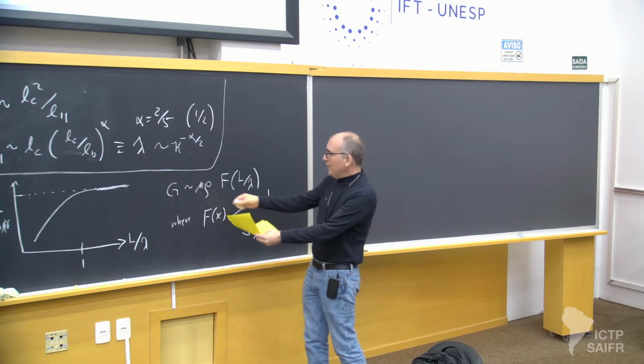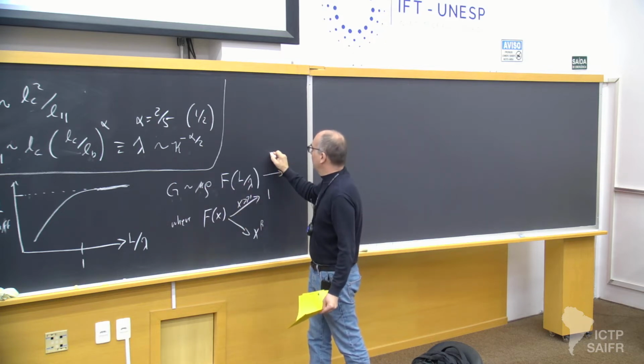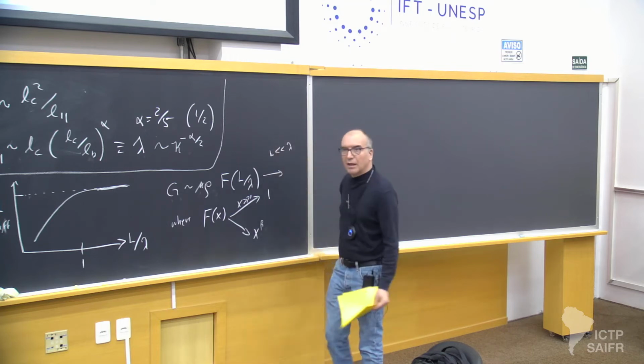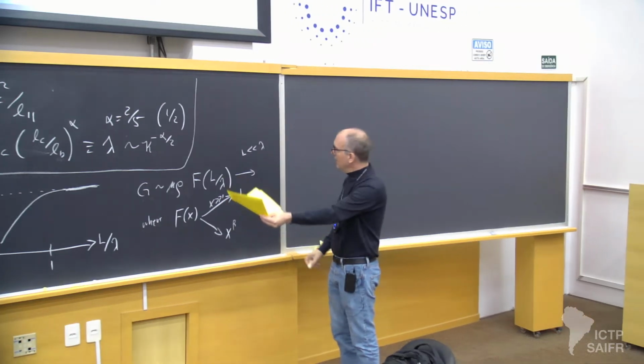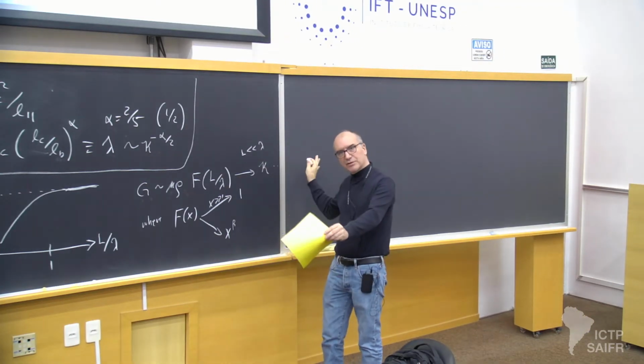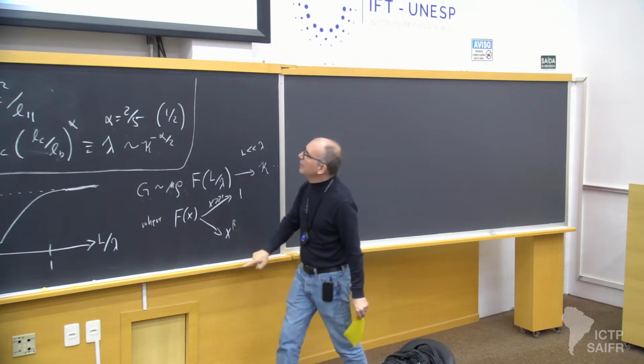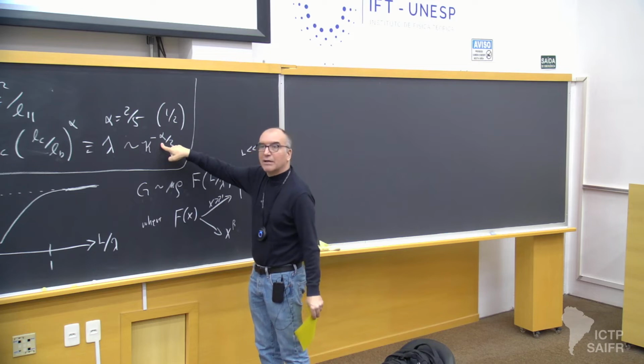But we know what the modulus here is in the limit that L is much less than lambda. It should be the non-affine one proportional to kappa plus other parameters. The only way I'm going to get a kappa here is if this power together with that power combines to give 1. Do you see that?